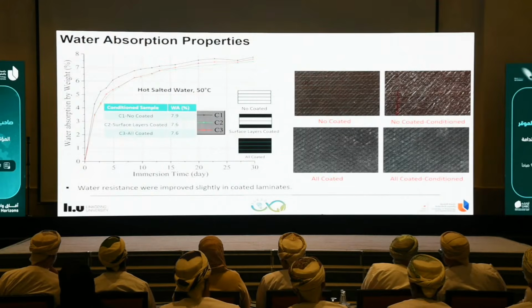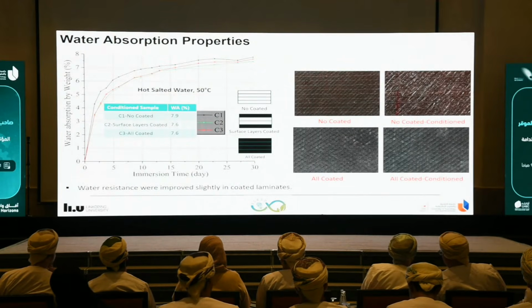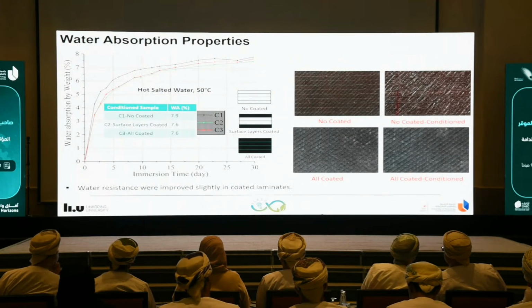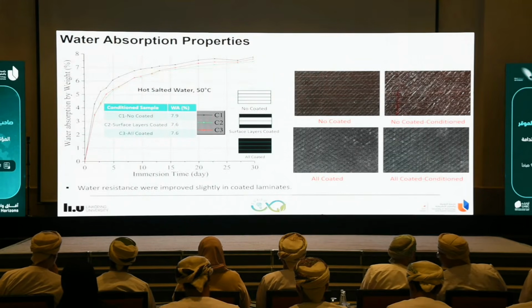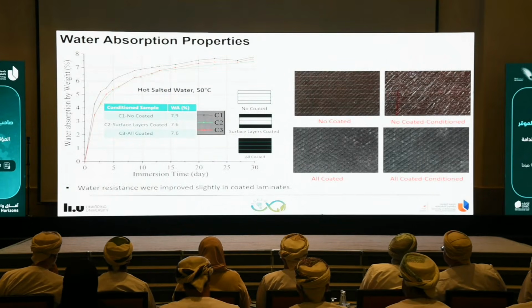But we did some analysis, and as you can see, the fibers which were not coated have degraded. However, the ones which were coated were not degraded. So the structure was still okay, but they absorbed water. And it's almost the same quantity, about 7% they absorbed in 1 month. So then we had the question, why?